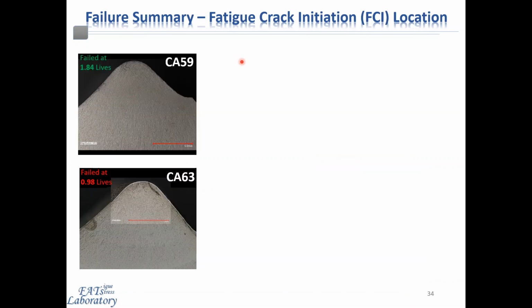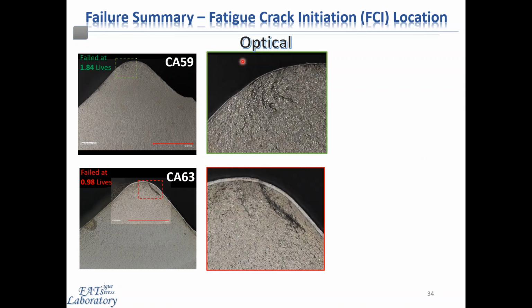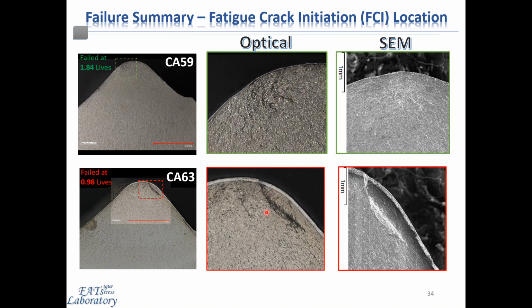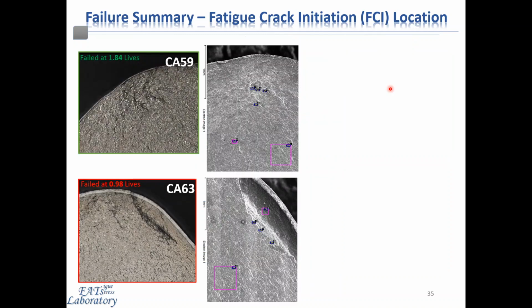So now zooming in even further on these pore fusion zones, we can use an optical technique, and we can clearly see some of the faceted morphology of the surfaces in these initiation locations. We also looked at the exact same locations, so we can see the exact same features here using SEM to evaluate the chemical constituents of the material in these localized regions.